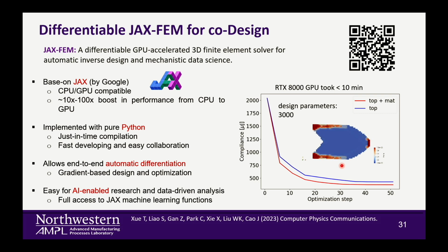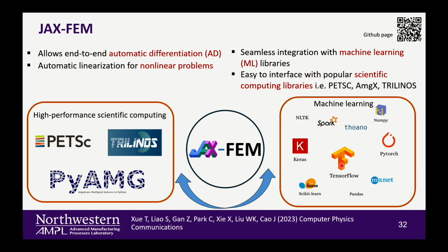And so if you co-design this with the geometry, topology, and the material together, you can see the red line gives you better compliance. It's actually about 13% better. And the potential of this is that you optimize like 3,000 parameters with the GPU in only 10 minutes. It's relatively easy because it's an elastic problem, but the goal is actually JAX-FEM right now. We have already incorporated elastic-plastic and hyperelastic into this. So what we try to do is bridge the physics-based simulation with the machine learning tools to speed up this numerical simulation.